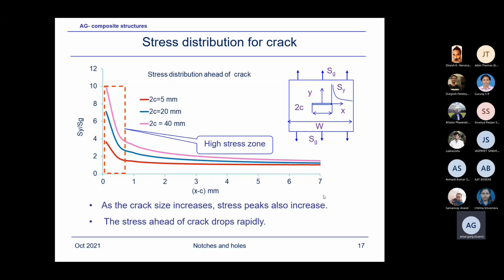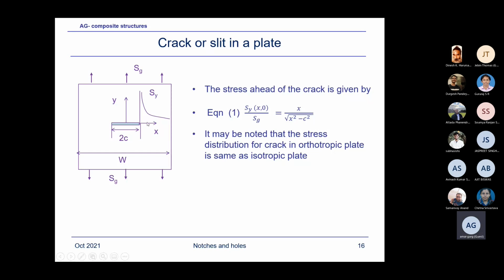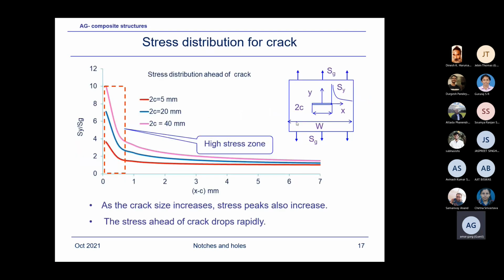Okay, now I've just plotted the stress distribution for the cracks. As you can see here, if you have a smaller crack, 2c equal to 5, then you find the maximum stress near the crack tip. Of course, right at the crack tip, theoretically, if I have x equal to c, right at this edge, the stress becomes infinite. That's a stress singularity, theoretically, from fracture mechanics. So here, of course, we have not gone to x equal to c because that will approach infinity. But what you can see, just away from the crack tip, the stress keeps on increasing as you increase the size of the crack.